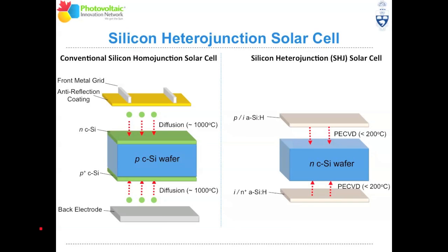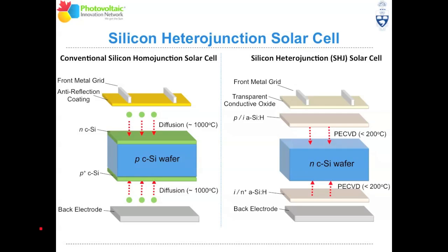You use a 200 degrees Celsius PECVD process to deposit a different material. And this different material is hydrogenated amorphous silicon onto the crystalline silicon wafer, on both sides of the crystalline silicon wafer, to form the rectifying and back surface field junctions. And then, much like the homojunction, you add a transparent conductive oxide, which also acts as an anti-reflective coating, and then your front and back metallization, and you have your complete cell.